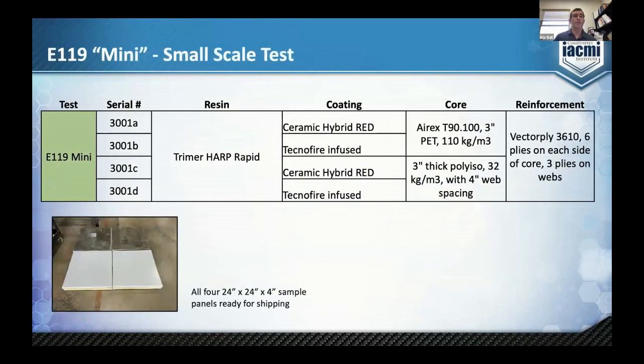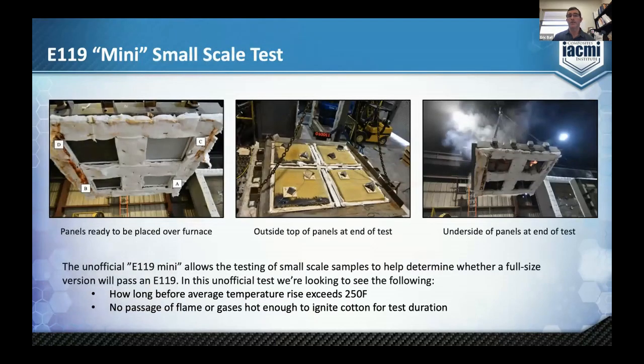So next we went to the E119 mini test. Again, we tested the ceramic hybrid red coating with Tecnofire, and we did two different cores. One was an Airex, so this is a structural core, and then we also did a polyiso core. The polyiso core was built with webs. The PET core had no webs. So this is a mini test. They're 2 foot by 2 foot panels.